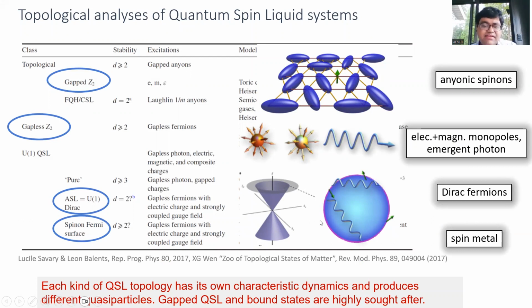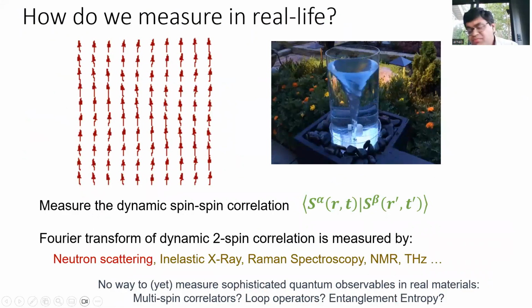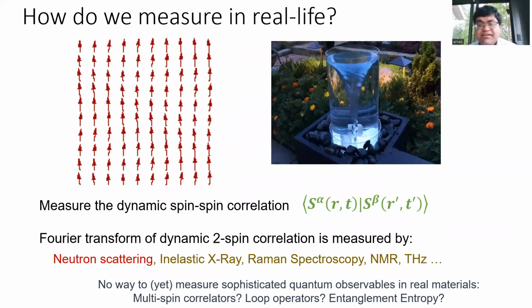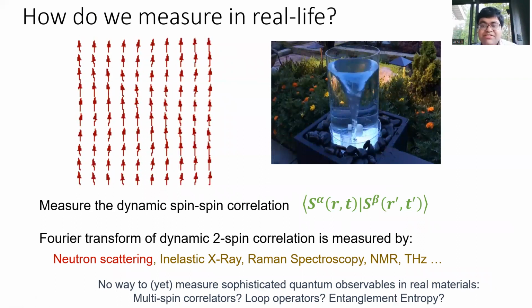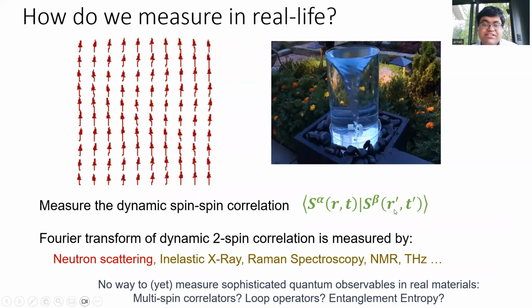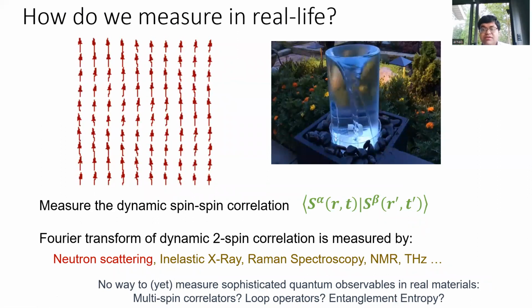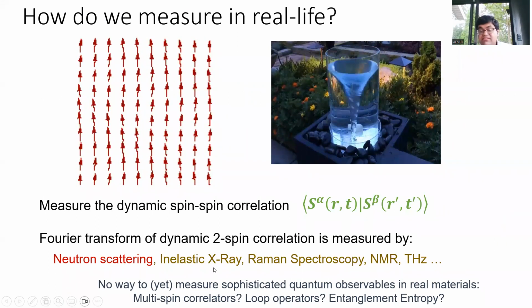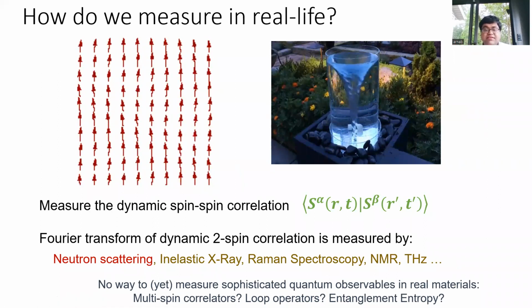The other important point is that the signatures of these quantum spin liquids are always apparent in the dynamics, as we just mentioned. So how do we measure these dynamics? The general way of measuring these dynamics experimentally is by looking at the spin-spin correlation. Whether you have some magnons or something more exotic or topological, what you finally measure is this quantity, the spin-spin correlation. And there are several types of measurements you can do in order to understand it. Among the important ones are neutron scattering, inelastic X-ray scattering, Raman spectroscopy, and terahertz.